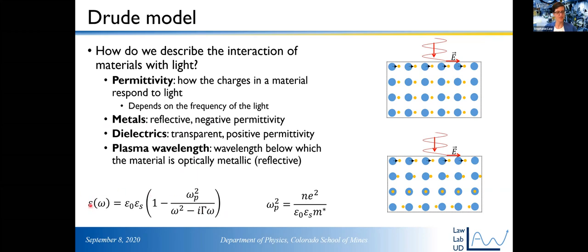So here's the permittivity. Like I said, it's a function of frequency, and it depends on, these are just some constants that I wouldn't worry about, but it depends on these quantities here. This is the plasma frequency, or I wrote plasma wavelength up here. I'm an optics person, so I use frequency and wavelength interchangeably. I apologize, I'll try to be careful about that in this talk. So the plasma wavelength, or the plasma frequency, tells you, for example, the wavelength below which the material is optically metallic, right? Remember, the permittivity is a function of frequency. So there is some wavelength below which it's a metal and above which it's a dielectric. That wavelength is the plasma wavelength, where the permittivity goes from positive to negative.